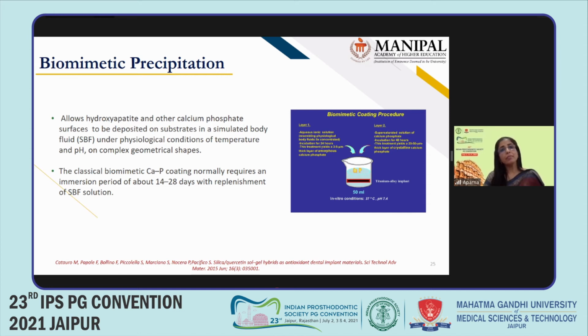Okay, so the classical biomimetic calcium phosphate coating normally requires an immersion of about 14 to 28 days. And it's important that there is a constant replenishment of the simulated body fluids. It is also observed that the thickness of the apatite layer increases as the immersion period increases. So it can be tailor-made. The manufacturer can plan and decide how much thickness of apatite layer needs to go on the implant surface.